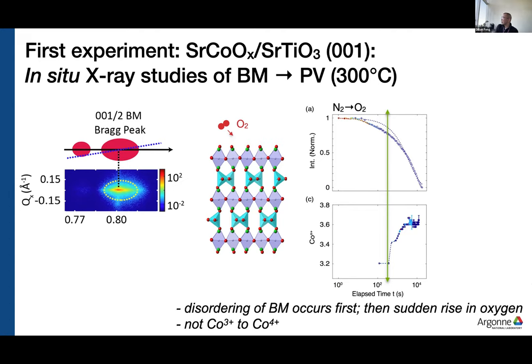But there's no change from cobalt 3 plus to cobalt 4 plus, which is what you would expect for Brownmillerite to perovskite. I would say that for these samples grown on strontium titanate, it's very hard to get pure stoichiometries. It's always somewhere between the Brownmillerite 2.5 phase and the perovskite 113 phase.